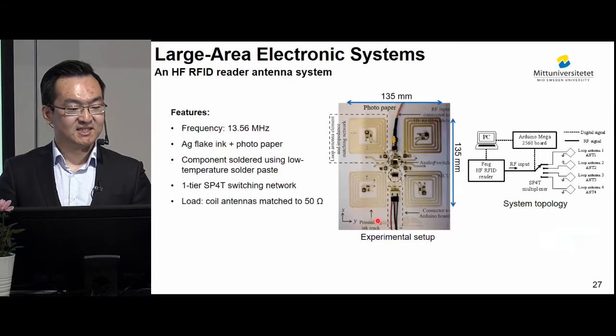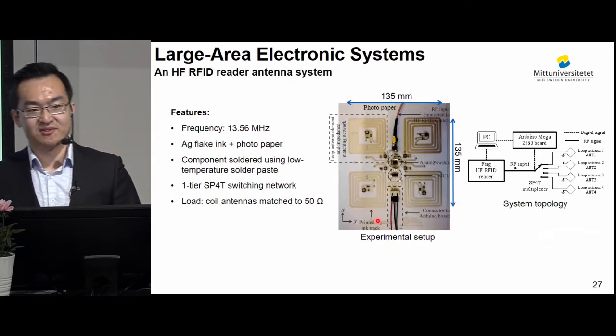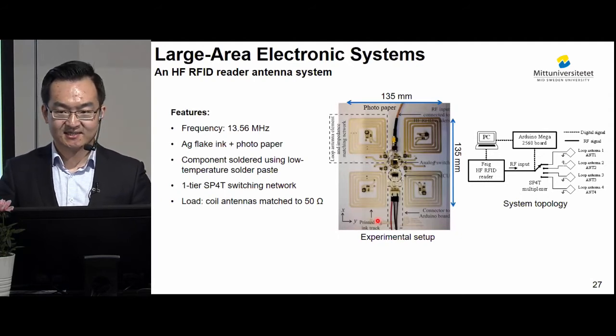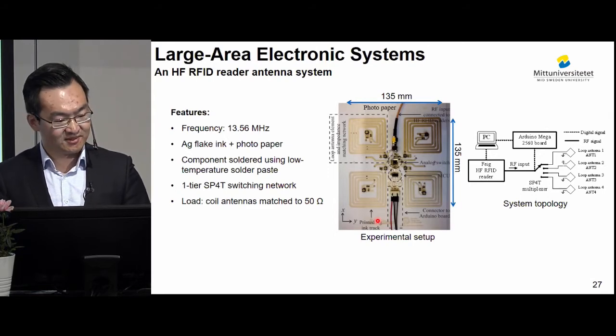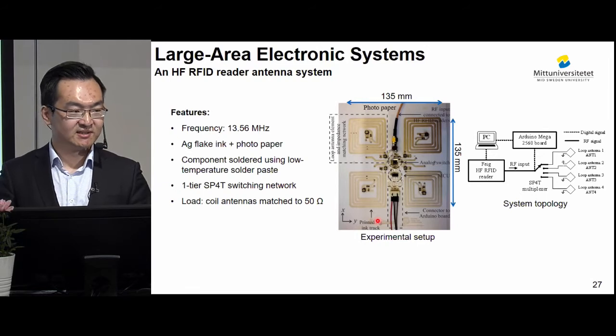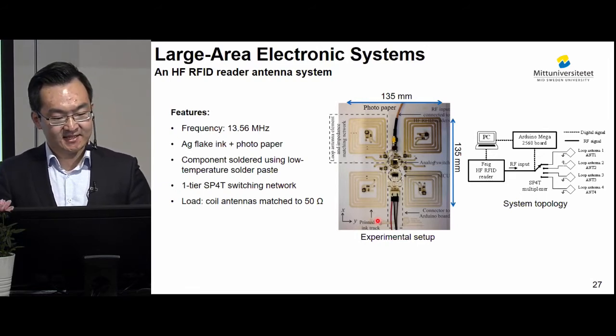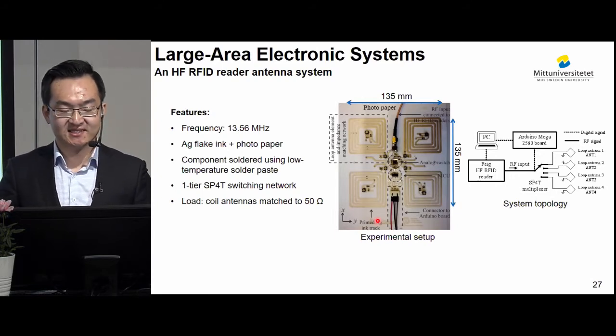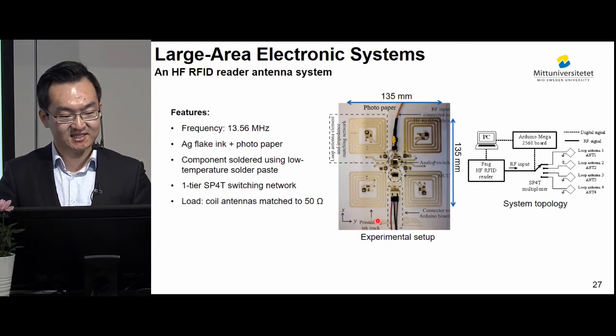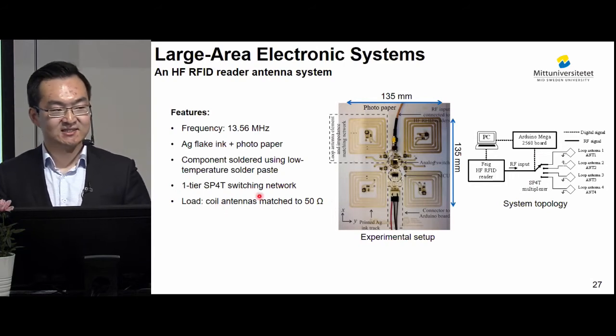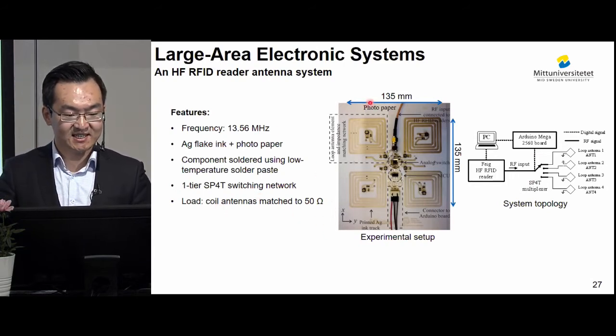The first antenna system is a reader antenna system that works at 13.56 megahertz. It is manufactured by screen printing silver flakes onto a photo paper with components soldered using the low temperature solder paste. And the previously mentioned low DC resistance method number 1 was used for this antenna system. And it is a 1-tier SP4T switching network with 4 antenna elements. And the antenna elements are coil antennas that are matched to 50 ohms. And this antenna has an area of 135 millimeters by 135 millimeters.